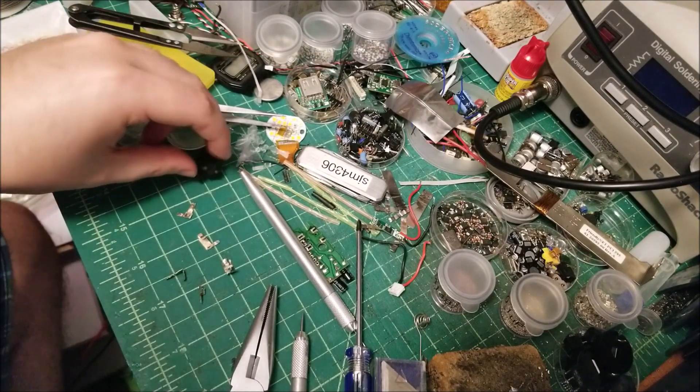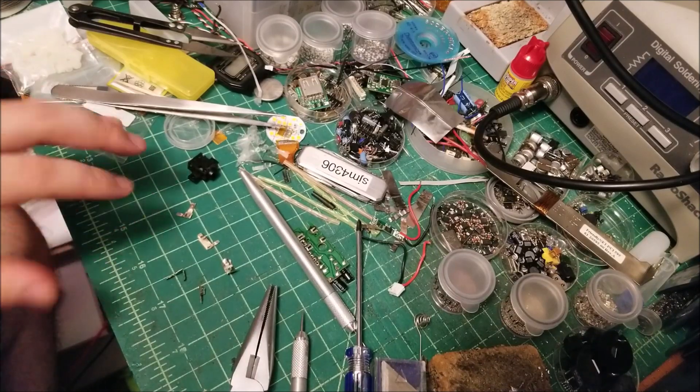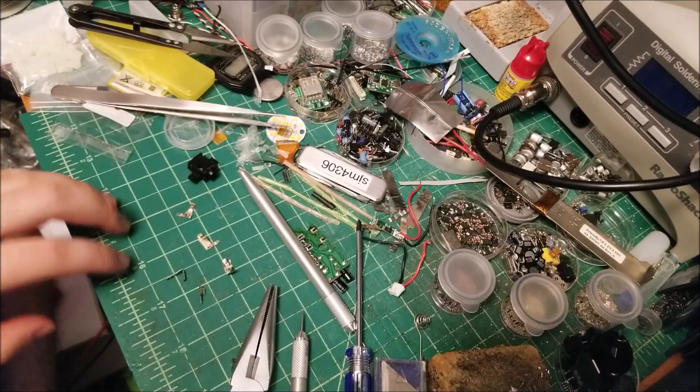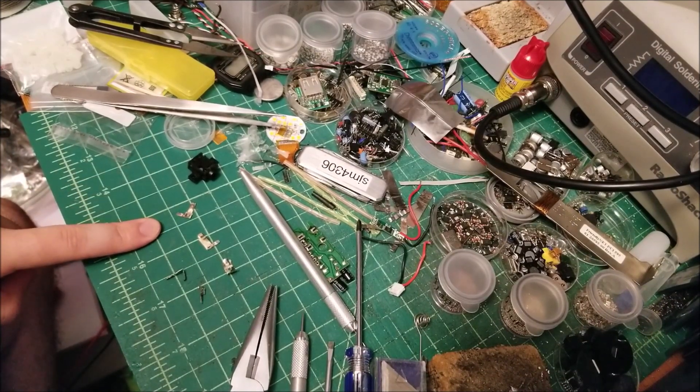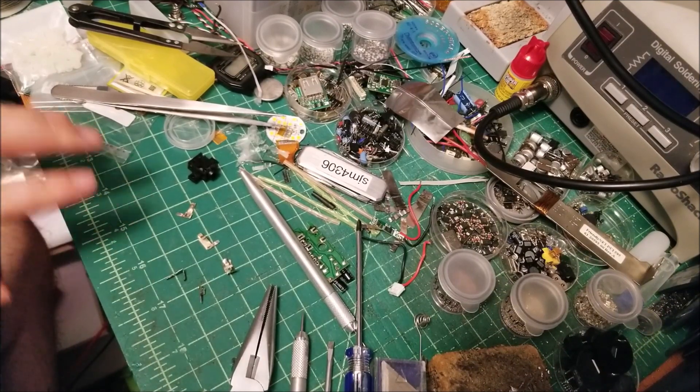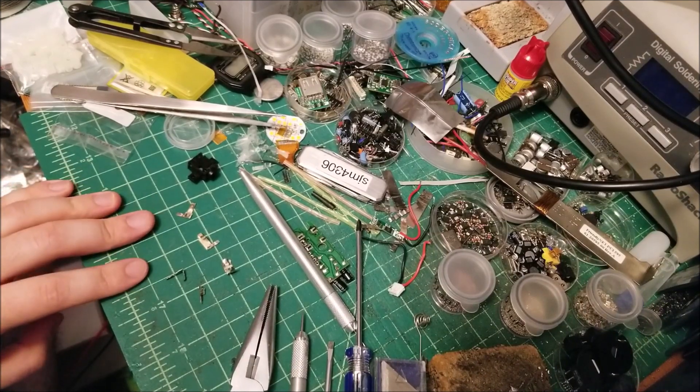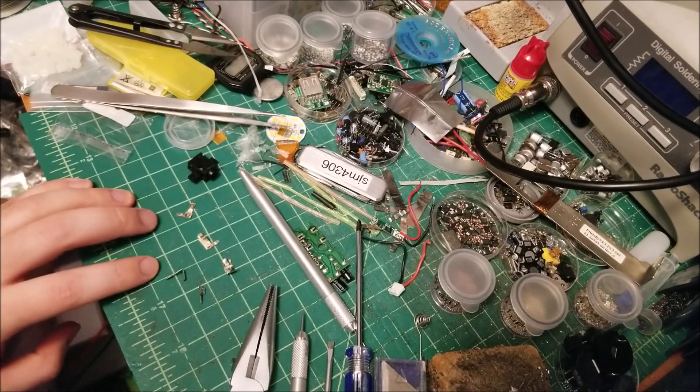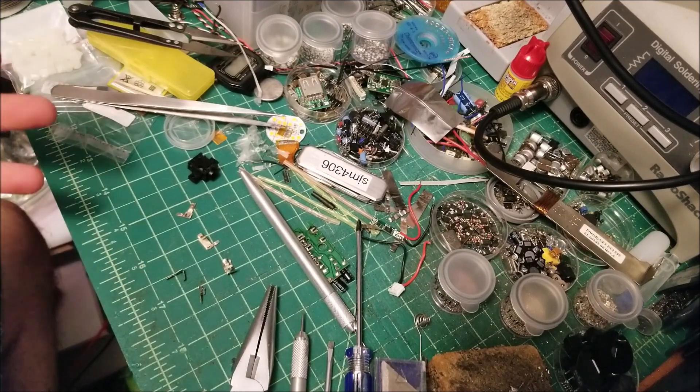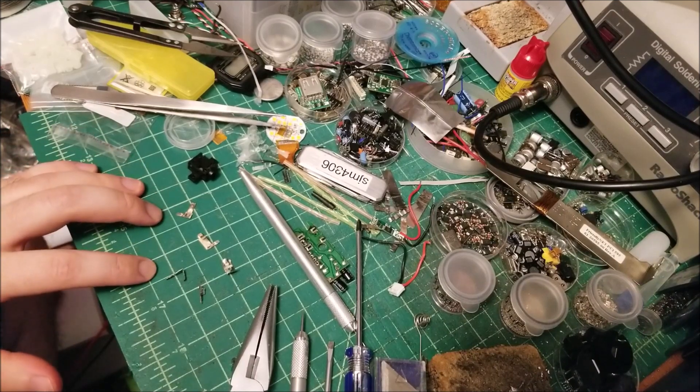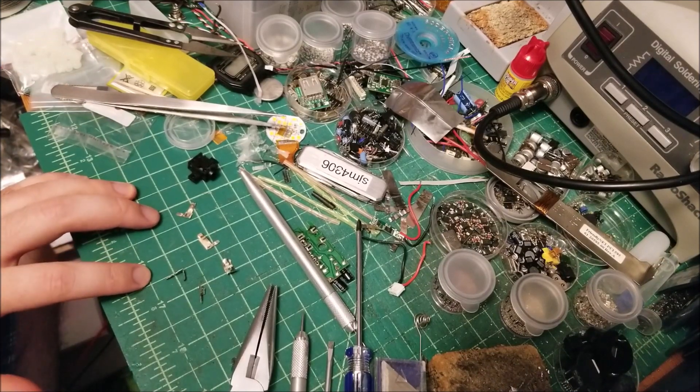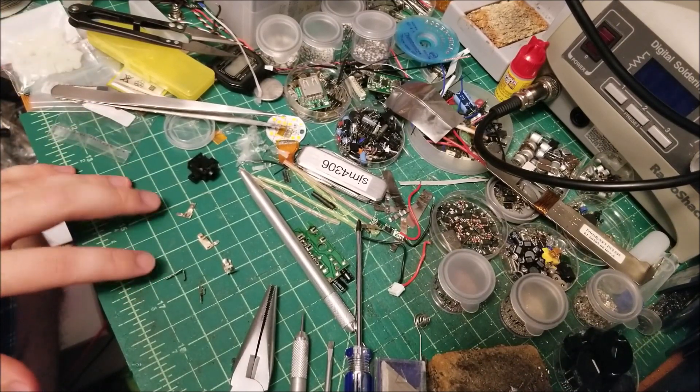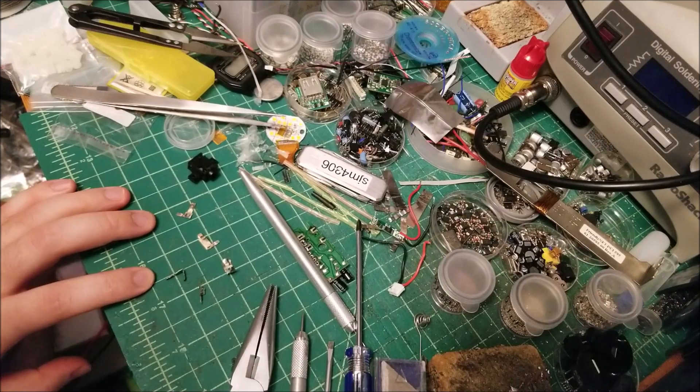Now what I'm going to do is scrub all these. First off, probably drop them in some vinegar to react any battery acid away. I'm going to do a second bath in isopropyl probably in the ultrasonic cleaner. And then I'm just going to take like a steel wire brush to it or something and clean them as best as I can. The plating is actually going to be gone on these likely. So even though I might be able to get them to work by cleaning them, it's probably going to be temporary, in which case I would need to nickel plate them again to prevent them from re-corroding just with moisture in the air. Because underneath the nickel plating on these contacts is very likely copper, just bare copper, and once that's exposed, it easily corrodes just with normal atmospheric moisture. So anyway, let me get on cleaning these.